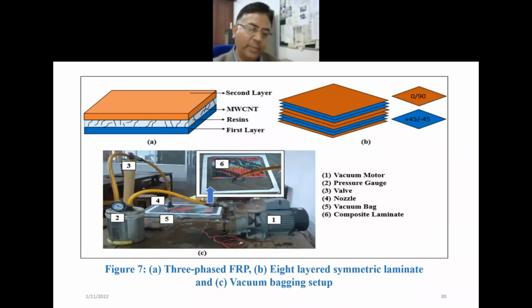So there also sometimes we make these materials by hand lay-up techniques, and without the vacuum bagging setup, we take the complete material made by hand lay-up and put it in that pressing machine, and then see the area of that. We have the top plate and bottom plate of that machine, find out that area, and then apply the pressure, how much pressure you want, which you can see digitally on the machine. You just set this pressure and temperature, let it be for a few hours, and then switch off the machine for the temperature, and after one day switch off the machine for the pressure. You can get a better laminate, good design and good fiber volume ratio, and a void-free surface. So these two techniques we are using in the lab for making the composites.